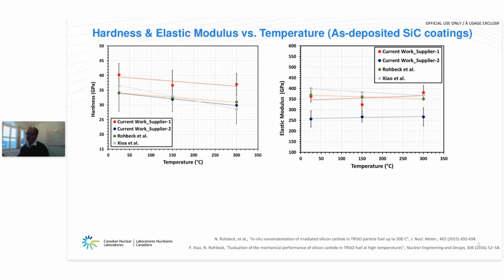One thing which I want to point out here is the assumption that we have been using the Poisson's ratio for cubic silicon carbide, which is 0.14, to measure the elastic modulus of these coatings from the reduced modulus that was actually measured by the indentation system.